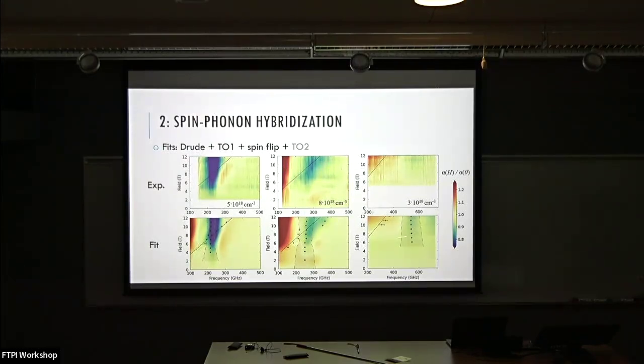Now, there's a lot of points here. I'm not going to go through all of this, but the main point is that there is a hint that you really see this anti-crossing. So the spin flip, of course, you don't see the spin flip when it's far from the phonon. You only see it when it's close.